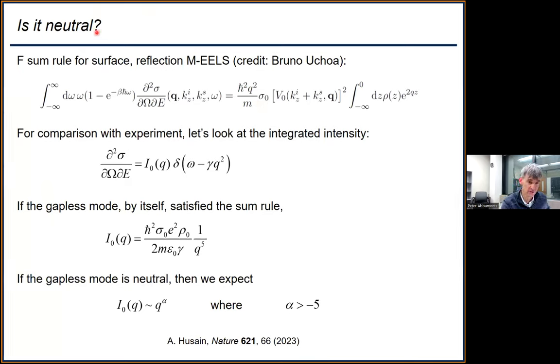We needed to close the loop and ask, is this thing actually neutral? To assess whether it's neutral, it's necessary to compare it to the F sum rule. A normal charged mode should go like Q squared, meaning the integrated intensity should go like Q squared. That's mandated by the F sum rule. So we wanted to do an analysis like that for this measurement.